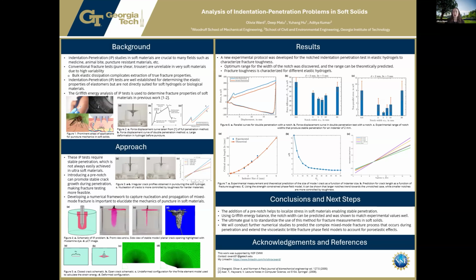Second, we discovered that there's an optimal range of notch widths that produce stable penetration. If the notch is too small, the indenter does not have a predefined crack path, and thus the crack will likely become unstable. And if the notch is too large, the system behaves like the unnotched case and will also likely become unstable. When the notch is in this stable range, the behavior is dominated by the fracture toughness, as shown in Figure 7C. And so this will allow us to extract this property accurately.